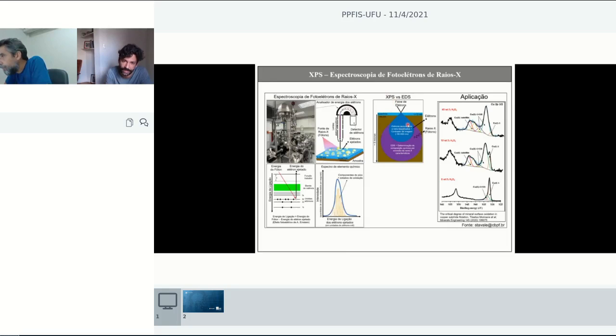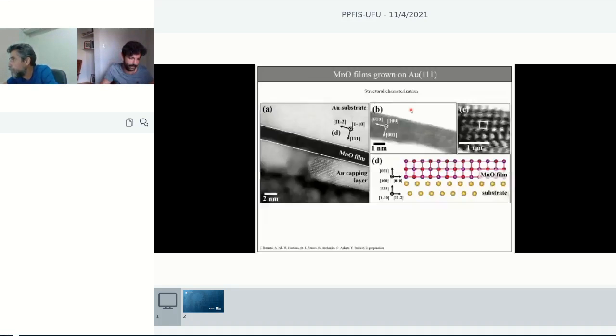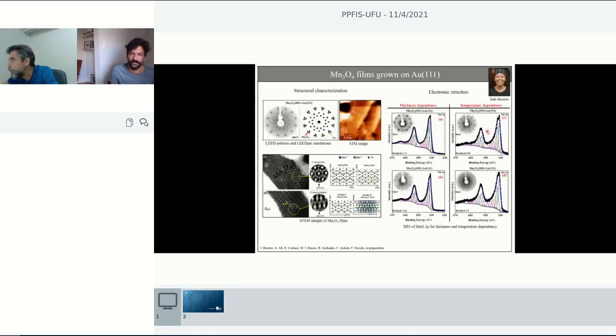here in the XPS, you actually get just electrons that are scattered. And these electrons can only conserve energy if they come from this region here, the surface region, between 1 and 10 nanometers. So this gives us a powerful tool to understand what's going on at the surface, and where the chemical reactions go on. That's why that result on the MnO is very important for us to judge how much of the things that we cannot see from an image like that, how many terrace atoms we have, how many defect atoms and kink atoms we have on the surface compared to the bulk atoms, because these atoms are the most reactive in any material, of course, because they are low coordinated atoms.